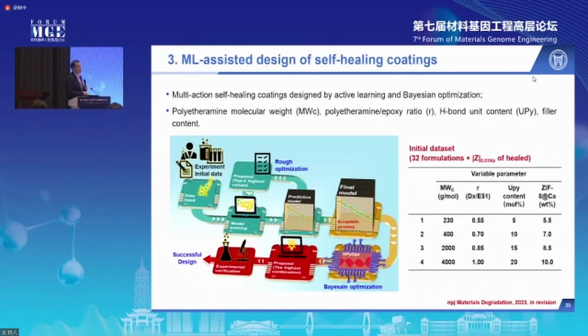We have also used data-driven approaches for a full coating formulation design. This is an example showing we use multi-action machine active learning and Bayesian optimization to develop a multi-action self-healing coating. The coating is actually quite simple. It has 4 basic parameters, including the polyetheramine molecular weight, polyetheramine epoxy ratio, and it is an intrinsic self-healing resin that contains hydrogen bond units for the reversible healing of the surface scratch. And it also contains fillers that incorporate corrosion inhibitors.